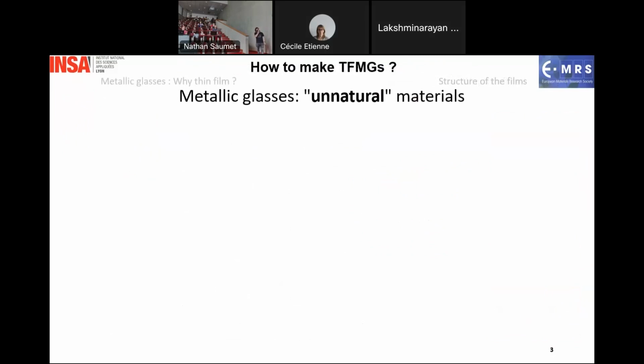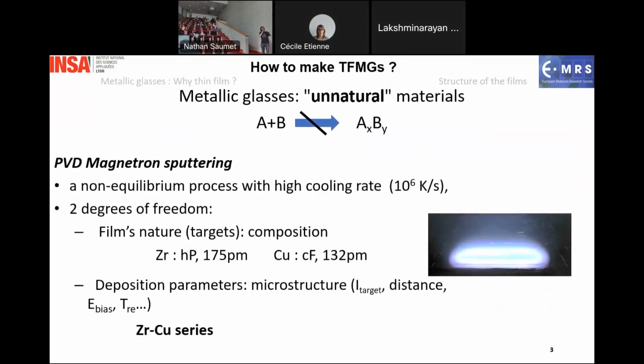Metallic glasses are kind of unusual materials because with two metallic atoms, we have alloys, which are well-known materials, but we do not want alloys, we want an amorphous phase. So we have to use a non-equilibrium process, magnetron sputtering, to create these metallic glasses with a high cooling rate. Important parameters are the composition of the thin film, where the two atomic species, here zirconium and copper, must have different atom sizes and also different crystalline structures. And we also have all the deposition parameters to control the properties of the thin films.